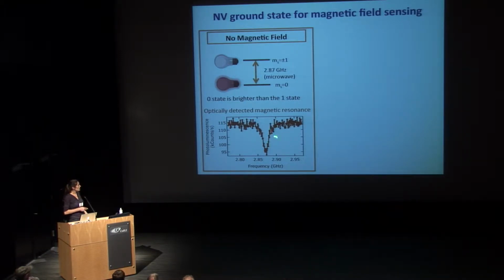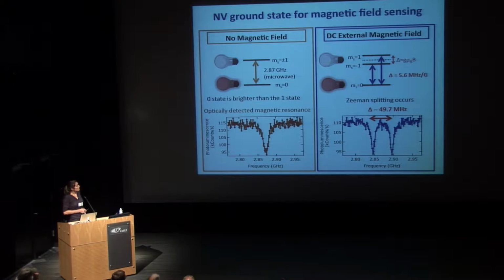We do optically detected magnetic resonance, and we see this signature at 2.87 gigahertz. In the presence of a magnetic field, this energy level, which is actually doubly degenerate, will be affected and split into two. The amount of the splitting is directly proportional to the applied magnetic field. We can see this peak split into two, and the amount of splitting is exactly proportional to the field, and hence we can infer what the magnetic field is.